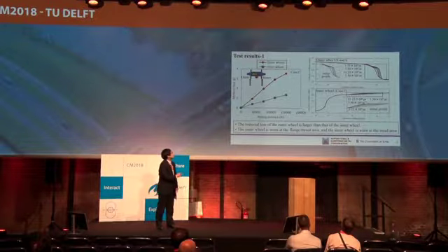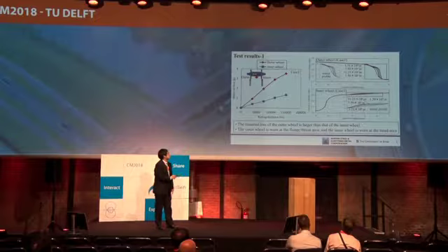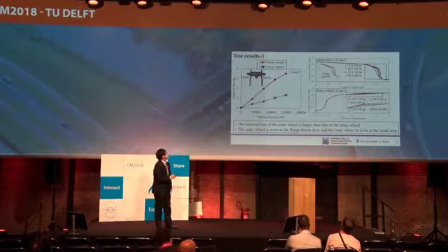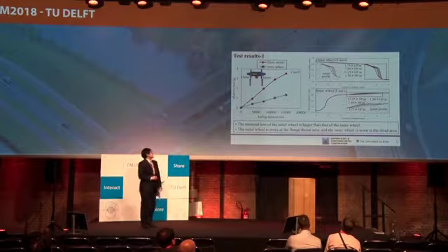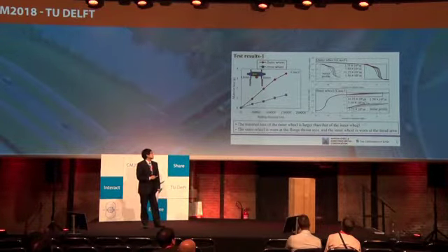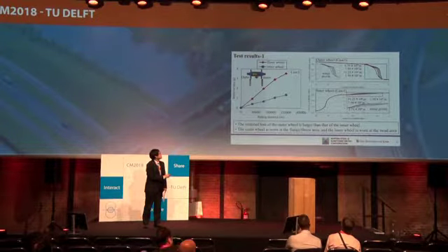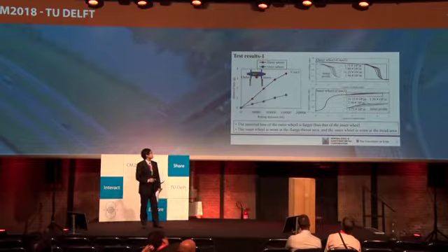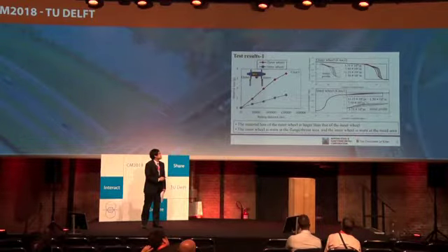And this figure shows wheel profiles for each test in case one, outer wheels and inner wheels. From this figure, the outer wheel wears at the flange and throat area, and the inner wheel wears at the tread area.